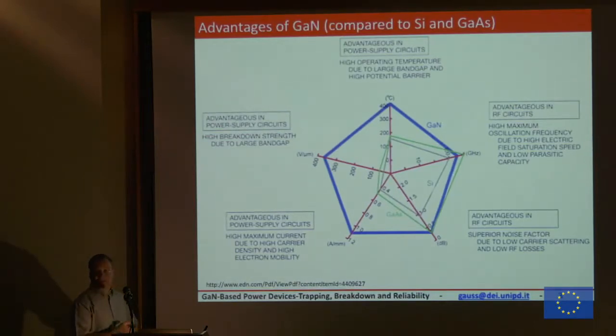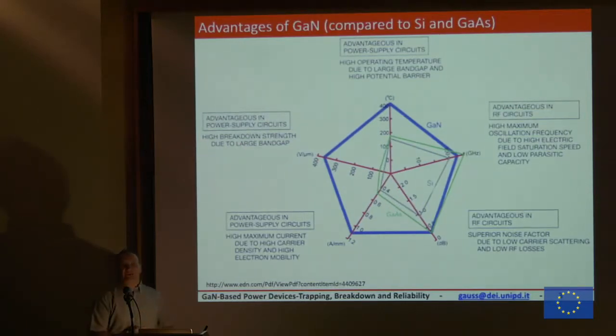The high breakdown, we have spoken about this a lot yesterday, and Peter also spoke about this physics behavior, so we know that we may have a very large breakdown in these devices. You see here that gallium nitride can sustain 400 volts per micron and silicon only 50 volts per micron. So if I need a 1000 volt device, I need at least a distance between contacts of 2 or 3 micron for gallium nitride, but I need 20 micron for silicon. So you may make devices much smaller, and because of the very high current density, much less wide. So my device is much more compact. That means we have much less parasitic capacitance.